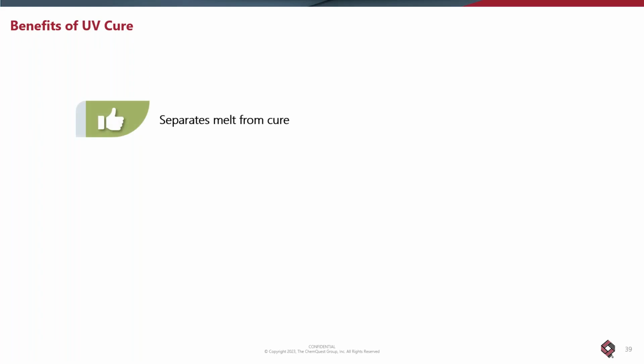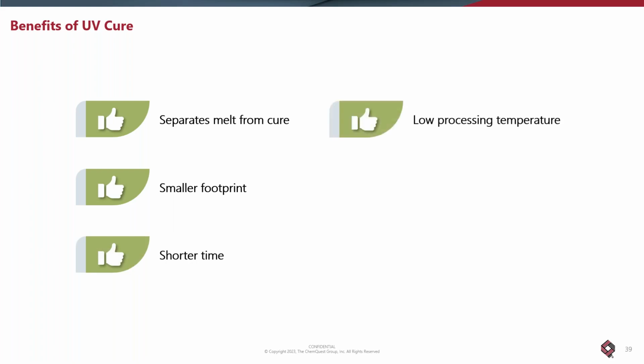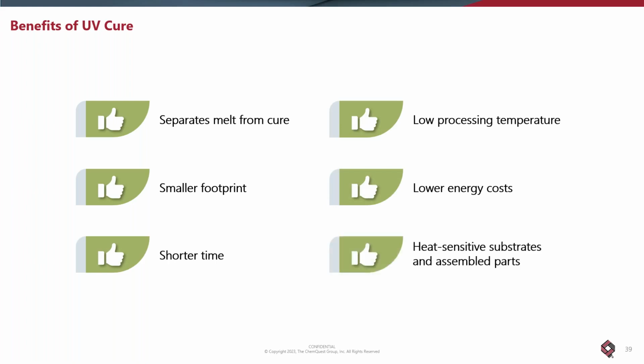Benefits of UV cure: I mentioned it separates the melt from the cure, so you don't have cross-linking in the extruder. You don't have to worry about that. You don't have chemical reaction in transportation or in storage. You have to get that intense UV light to get advancement. It's a relatively small footprint. You can do it all in a pretty small space, a short production line, finishing line, short time frame, low processing temperature, low energy costs, and it really can be a good option for substrates that can't take temperatures beyond, say, 125 to maybe 140, 150 Celsius.